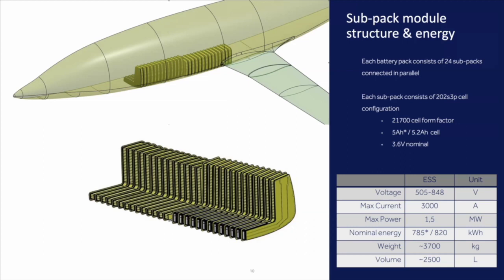From a C rating perspective, we're actually the best customer you can imagine. We cruise at roughly 0.4C, we take off at roughly 0.9 to 1C, and even in an emergency condition, a rejected landing that requires a high power back in the air situation, we are looking at roughly 1.5C from a situation where we lost part of the battery. So from an amperage perspective, not as bad.